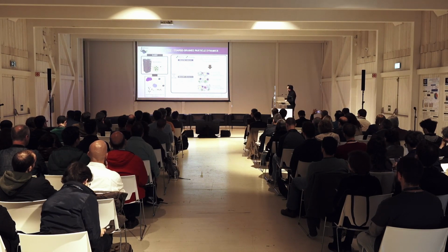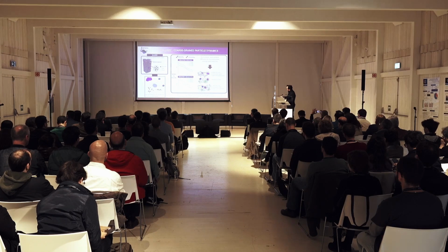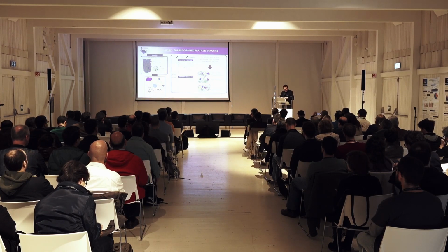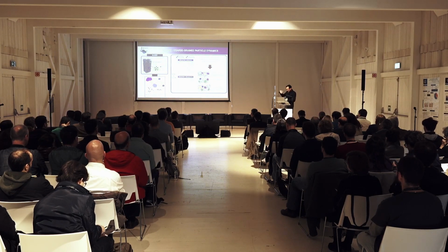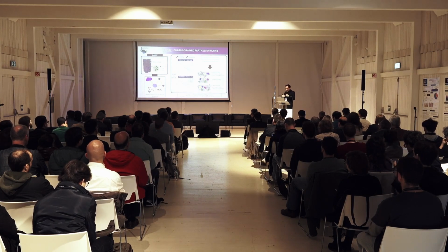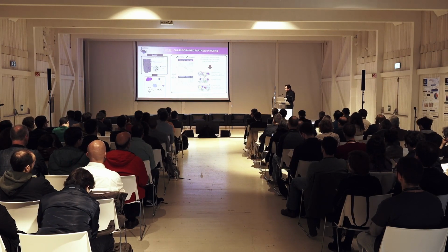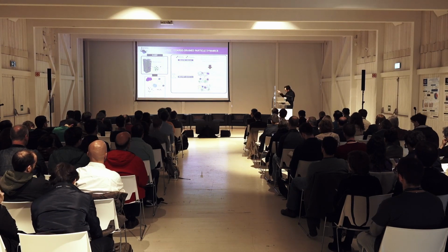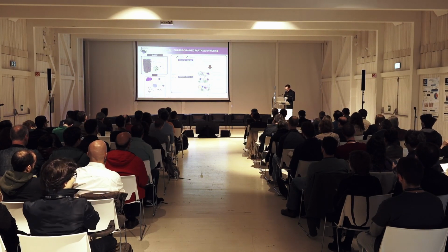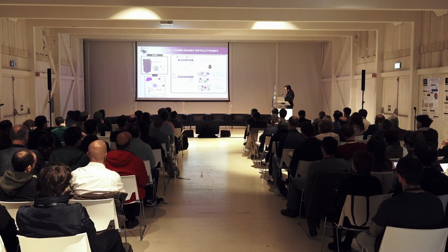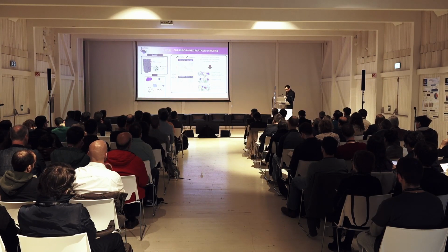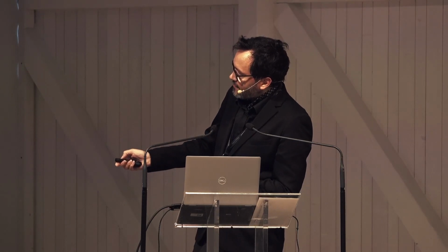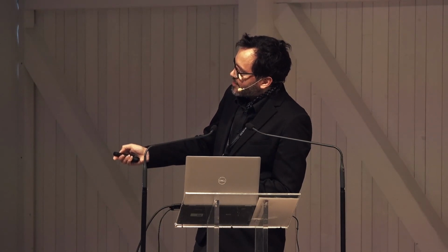And this digital twin of the slurry can be validated in terms of properties that we can measure experimentally, that you can calculate in the computer, and then with back and forth with the experiment, you can see if your calculations are correct or not. And if they are not correct, you will fit the force field parameters in order to match the macroscopic properties of the slurry that you observe in the experiment. And here we deal with the density and the viscosity as a function of the applied shear rate. You see here an example of comparison between the calculated viscosity as a function of shear rate for different solid contents and for two different formulations of the slurry, showing that the model works well.